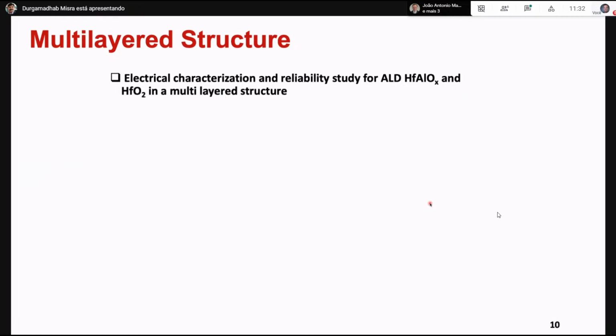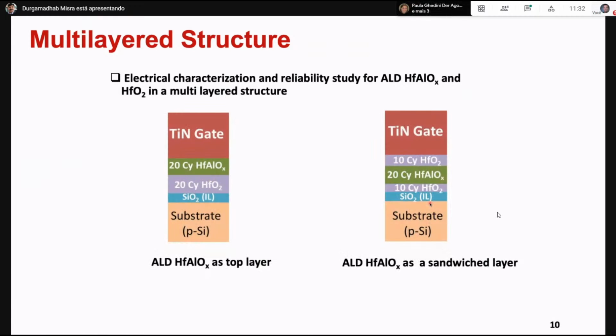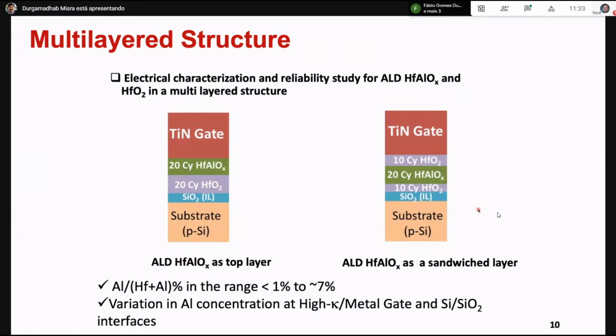Here is one example of a multi-layered structure you can deposit, because you start with a silicon interfacial layer, and then you go for the 20-cycle hafnium oxide and then hafnium aluminum oxide. That way you can control, or you can go for a sandwich structure like this, and control the amount of aluminum that you introduce in hafnium oxide. It is done by cycling, while the thickness can still be around 2 nanometer or 2.5 nanometer. You can control the aluminum introduction inside hafnium oxide to 1 to 7%, which was very difficult before, because you would do either aluminum oxide or hafnium oxide, and now this ALD process allows it.